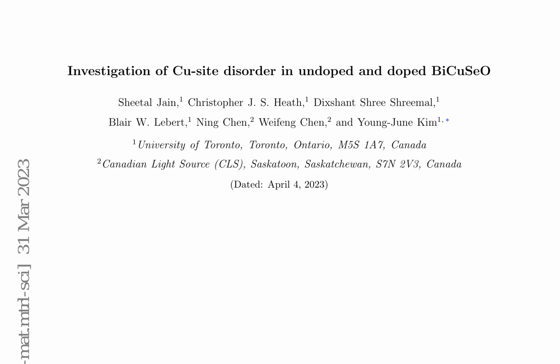However, Ag K-edge EXAFS results indicate that Ag replaces Cu in BiCuSeO, with no evidence of alternate dopant locations. Given that Ag doping does not increase the static disorder parameter, it can be concluded that Ag uniformly replaces Cu atoms. The mass defect resulting from Ag replacing Cu, combined with the retained disorder of the Ag dopant, may be the primary reason for the reduced thermal conductivity. Notably, EXAFS results show large sigma-squared values along the Ag-Cu and Cu-Ag atom pair, while values along Ag-Se and Cu-Se are significantly smaller.